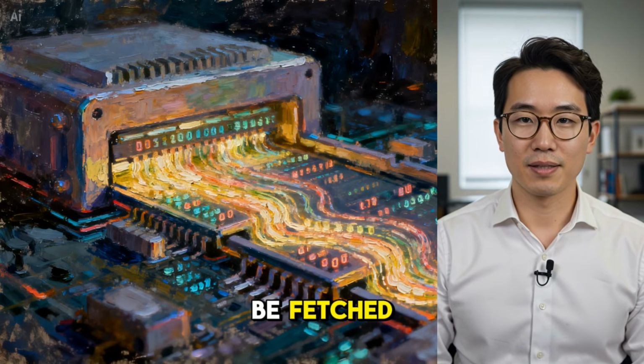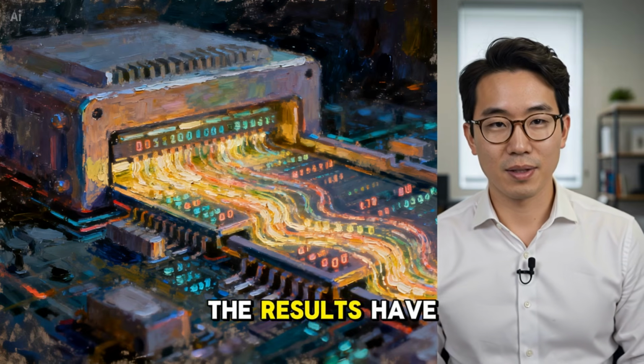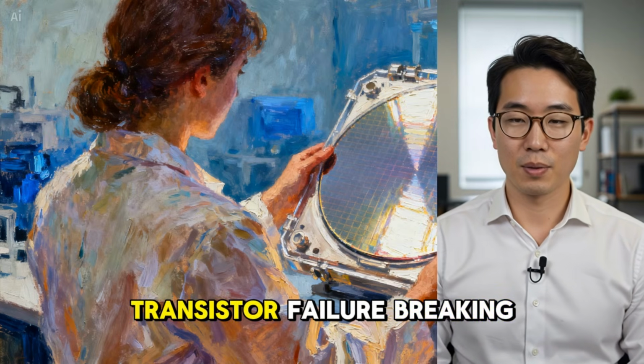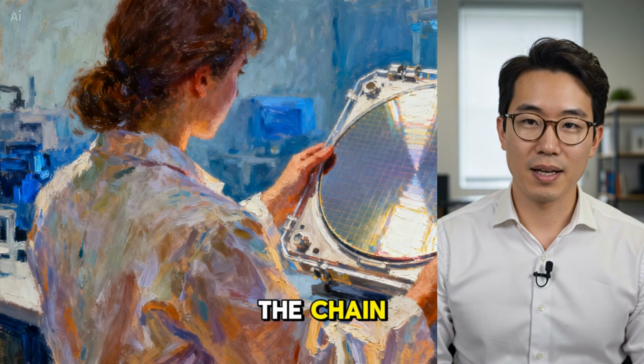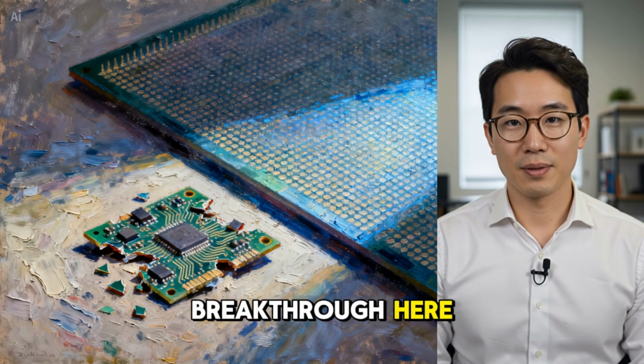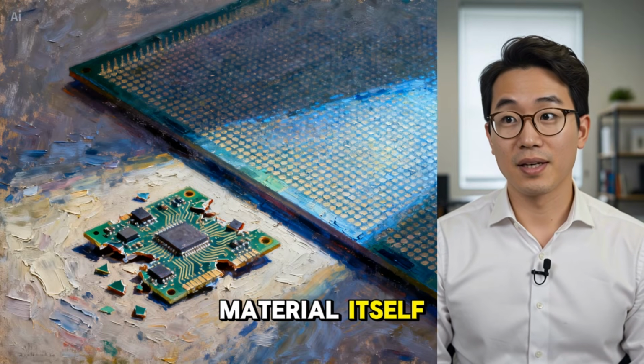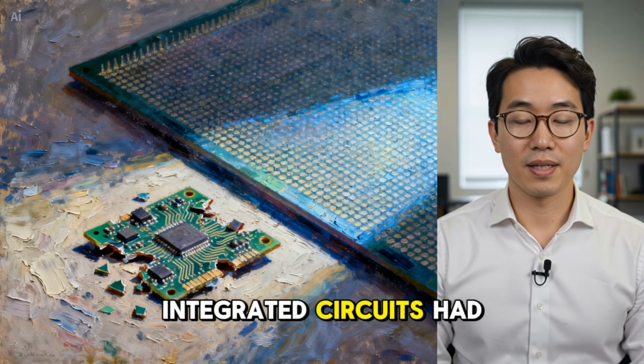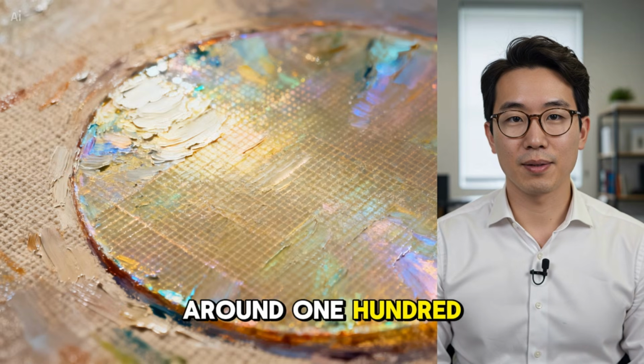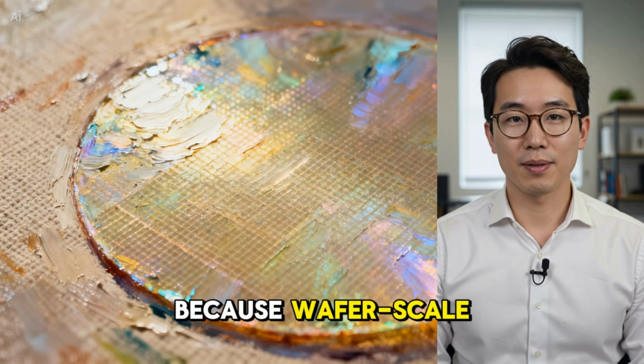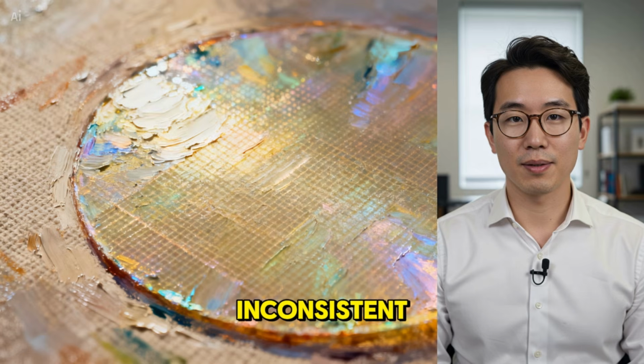Instructions have to be fetched, decoded, executed, and the results have to be stored, all without a single transistor failure breaking the chain. Manufacturing consistency was the real breakthrough here, more than the material itself. Previous attempts at 2-dimensional integrated circuits had topped out at around 100 transistors, according to the research team, because wafer-scale 2-dimensional films are notoriously inconsistent.